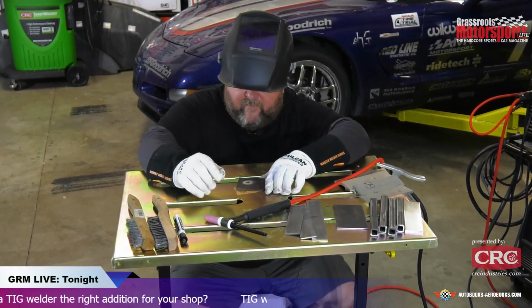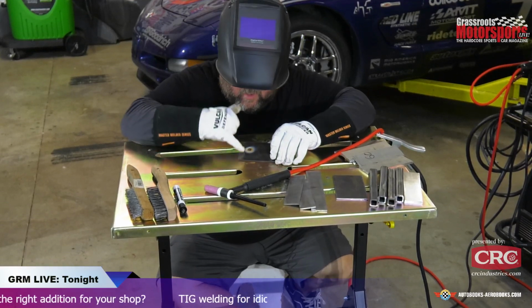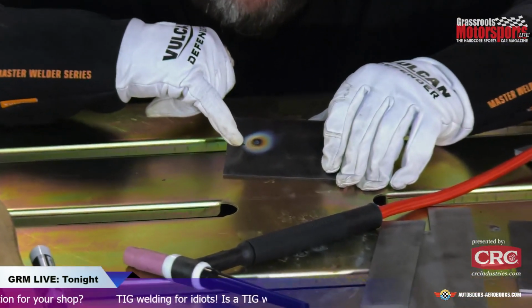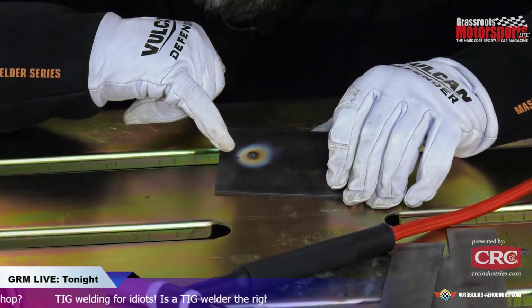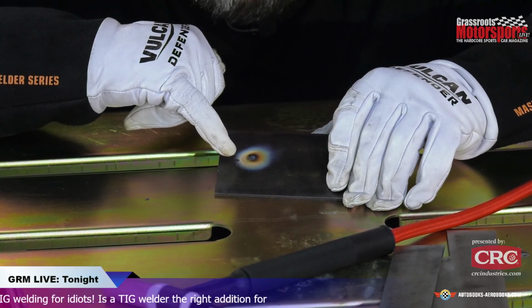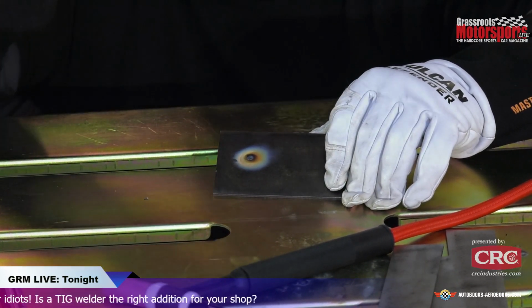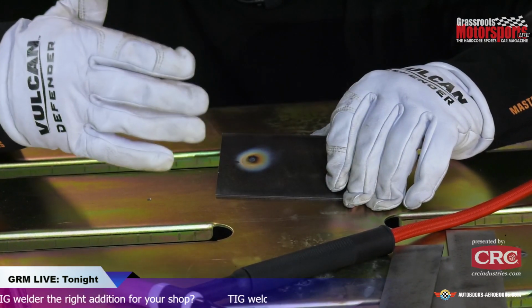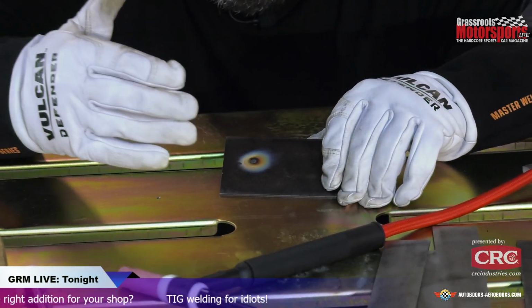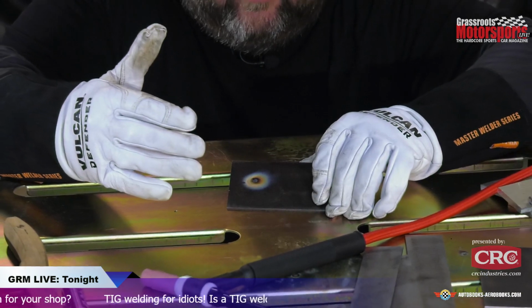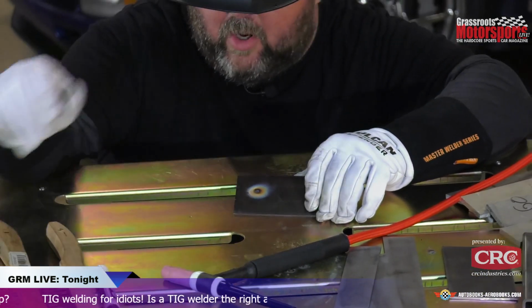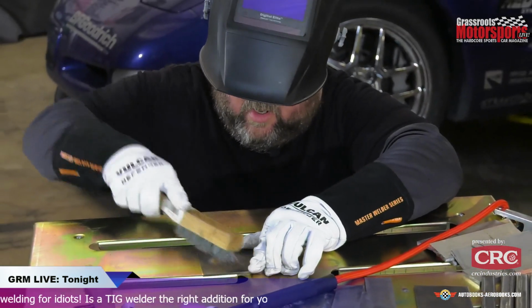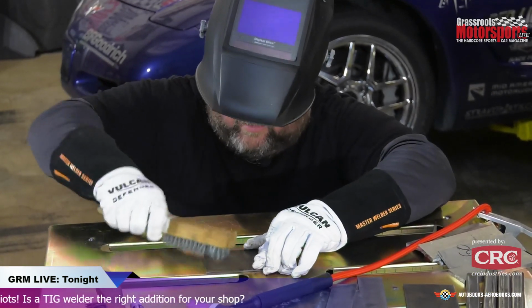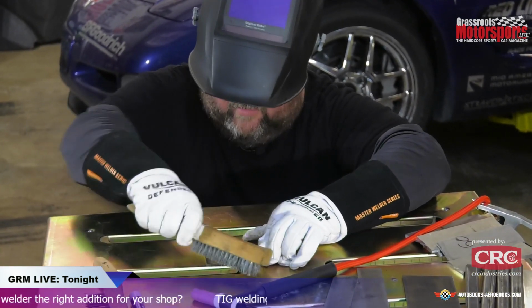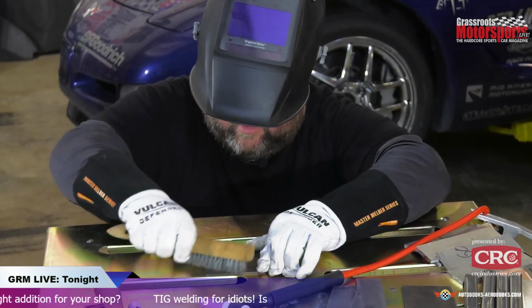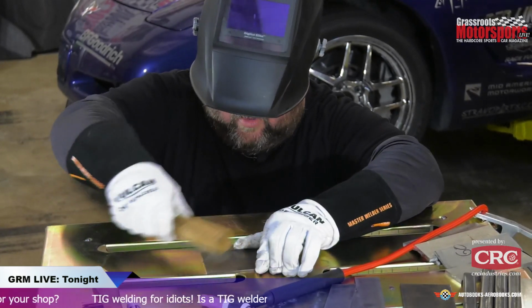Well, here's our first good lesson of the night. Here's what happens when you don't have adequate gas coverage. Look at all that soot around the outside of where our puddle was. All that soot is a byproduct of the fact that we did not have a stable atmosphere. We actually had a surprisingly good arc, considering we had a garbage atmosphere around there. But all that soot, which is going to be essentially contamination in the weld, is a byproduct of not having that stable atmosphere to work from.